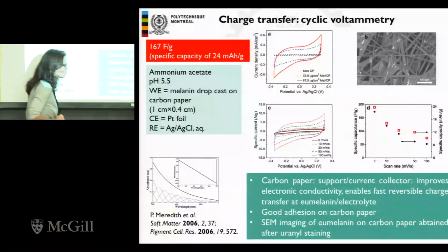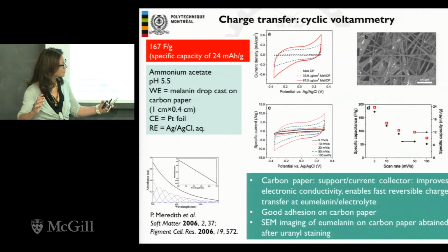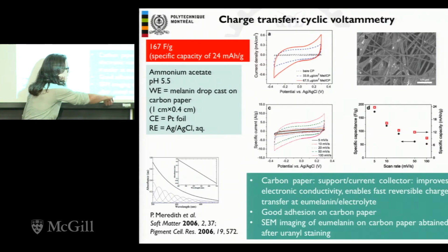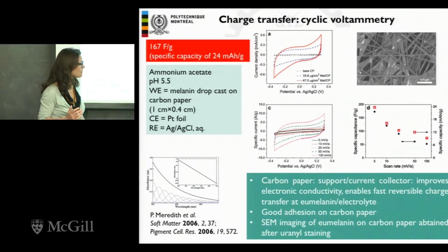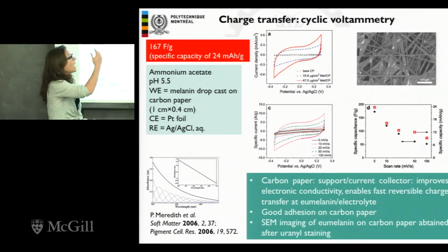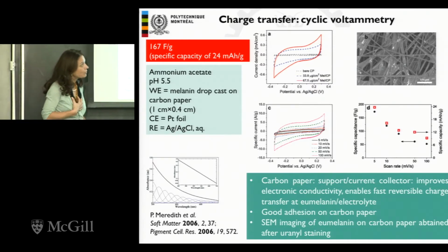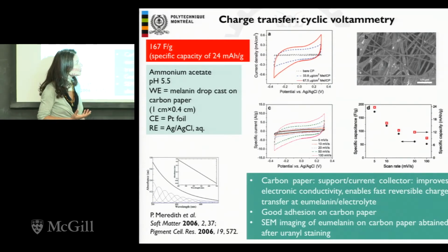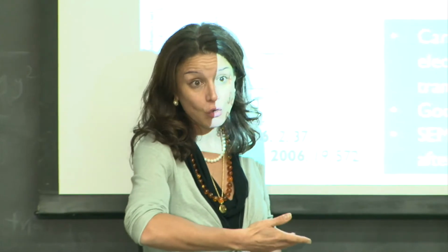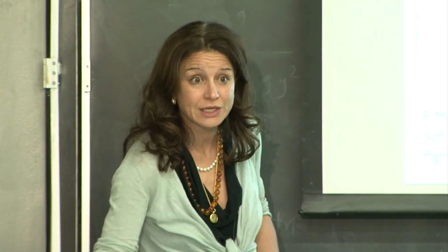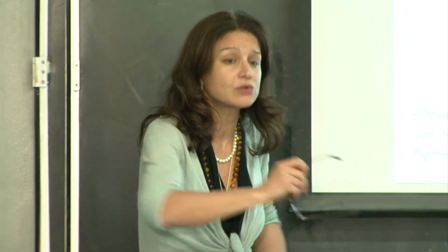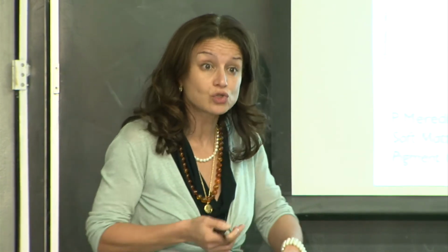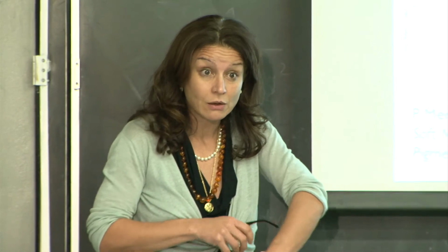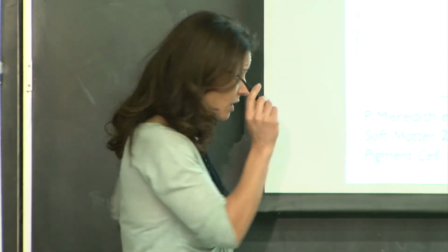Okay? And what we used was actually a uranyl staining approach. So we said that melanin has good ion binding properties. This salt is no exception. So we were able to stain our melanin with a heavy atom. We were able to reveal where our melanin is on the carbon current collector. For me, there are implications; it was also a way to explain to the students the continuity between disciplines. You work in science, there is no clear frontier between one discipline, one interest, and the other. So we should develop this intuition in the sense that if uranyl stains well my melanin that I want to image for my specific electrochemical energy storage device, there are good chances that melanin also blocks uranyl salt in my skin. Okay, so there are other types of consequences we should be aware of.